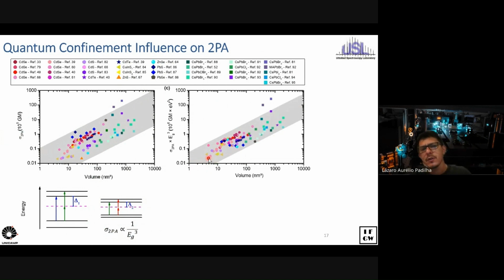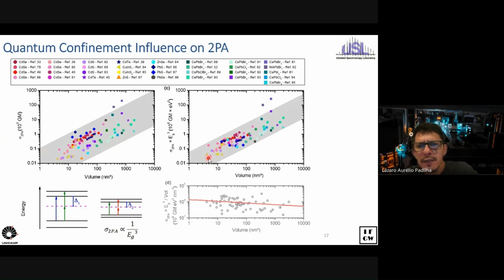And one thing that's even more interesting is that if you just think about this and divide by the volume to look at the volume normalized two-photon absorption, it's basically flat with the volume. If you want, there is a little bit of a slope here that indicates that making it smaller makes it a bit better, but honestly, this slope is pretty tiny. When you go through about 4 orders of magnitude in volume, your volume normalized two-photon absorption cross section changes by a factor of 2, roughly. So I could tell you that it's nearly constant.